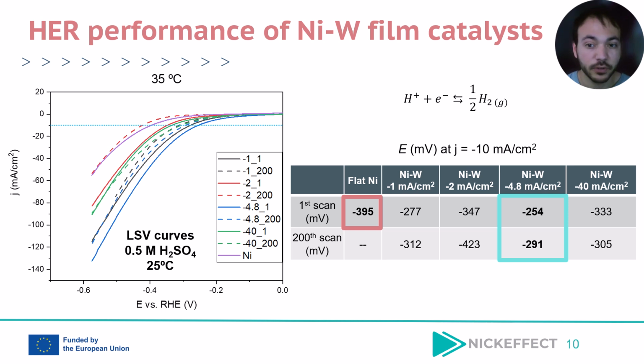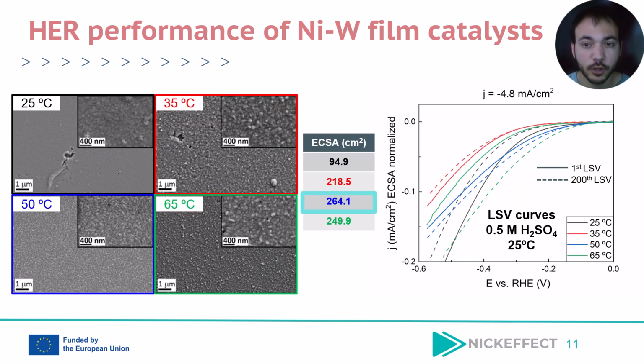The performance of the samples was tested versus a sputtered nickel substrate that has one of the worst values, and also it did not resist the full 200 cycles. After obtaining the optimal current densities to deposit the film, we went back to further study the morphology of the samples, since, as mentioned before, there's a big difference between the morphologies of the substrates, once observed at the nanoscale with SEM. The electrocatalytic surface area of the samples was measured, obtaining the expected results, where the sample at 25 degrees has the lowest ECSA due to the smooth surface, and the other sample has the highest due to the acicular grains.